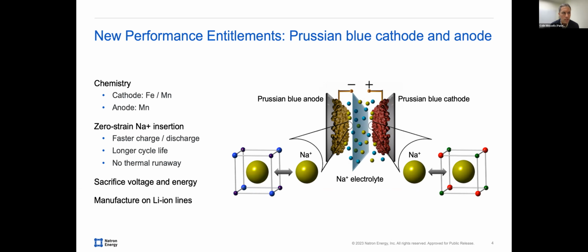And the key innovation that we had here at Natron was we identified that the atomic structure of Prussian blue is effectively a sponge for sodium ions. And as you can see in the schematic on this slide, this atomic structure is represented by these cubic cages, and the empty spaces in the middle of each cube is just the right size for a sodium ion. So you can imagine water being absorbed into the pores of a sponge. You can squeeze the sponge, get the water back out. It's reversible, it's very fast. The same is true for Prussian blue and sodium. We can absorb and release sodium ions very, very quickly.